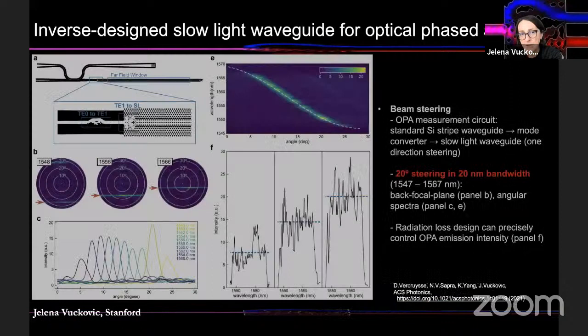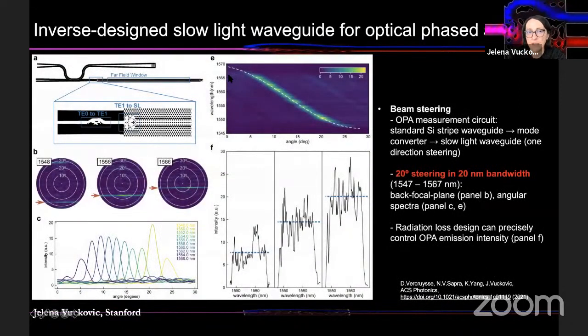And then when we implemented everything and fabricated, we measured this beam steering. So this beam steering is essentially dispersion of the structure, and you see that as you change the wavelength of the input laser by 20 nanometers, you have this linear dispersion regime, and you tune the output angle by 20 degrees.